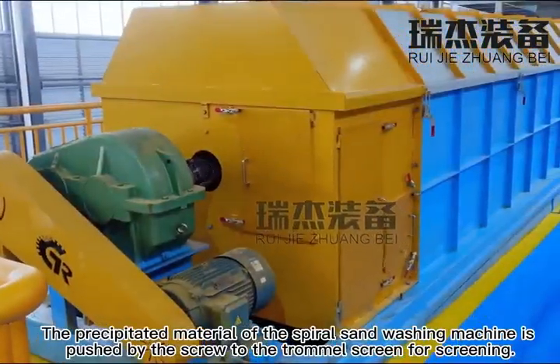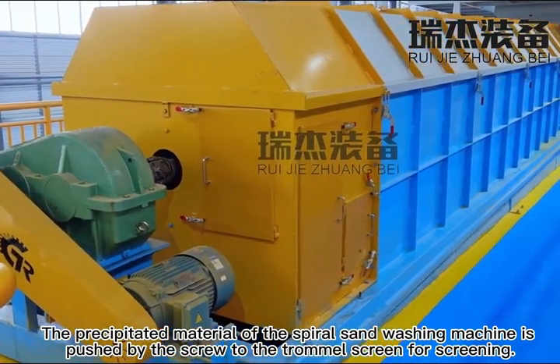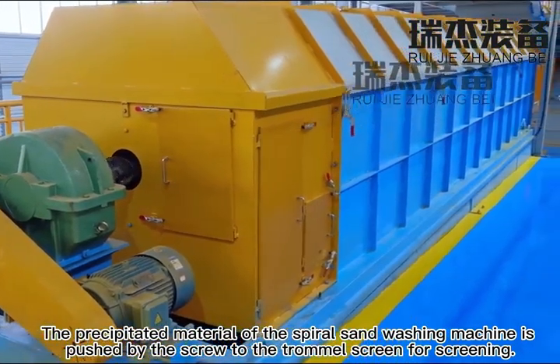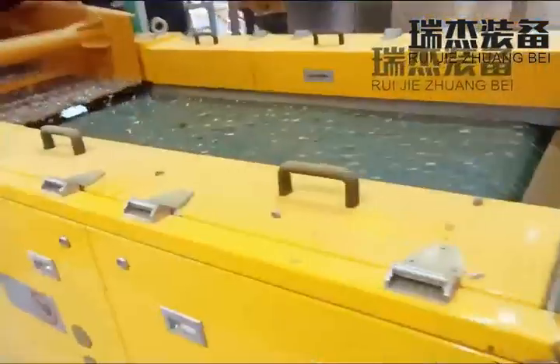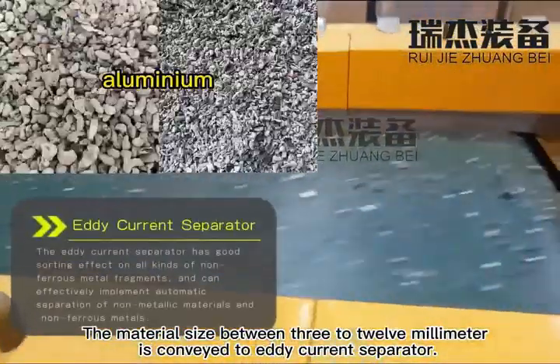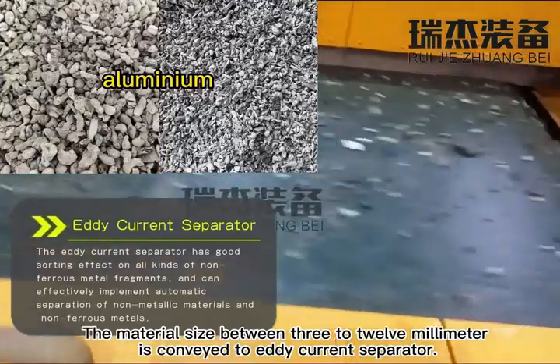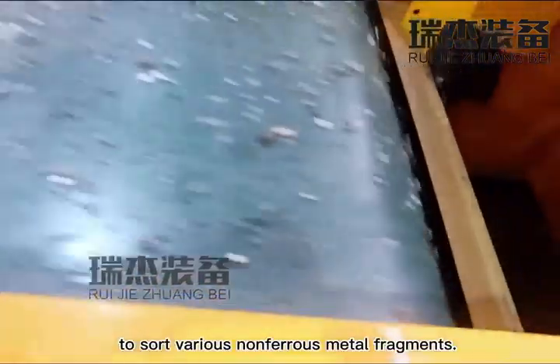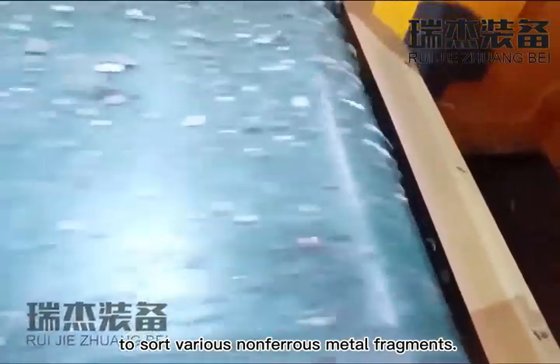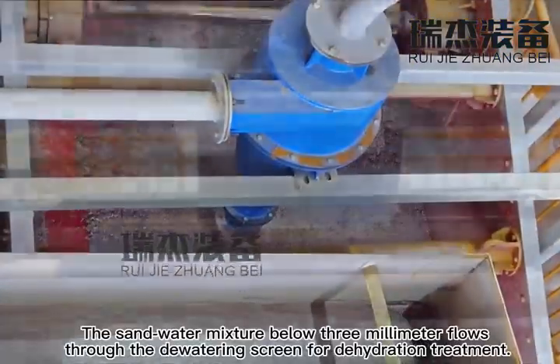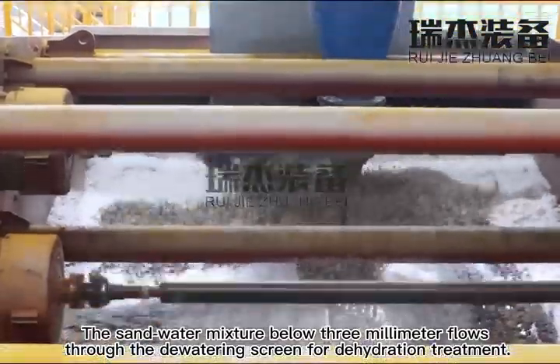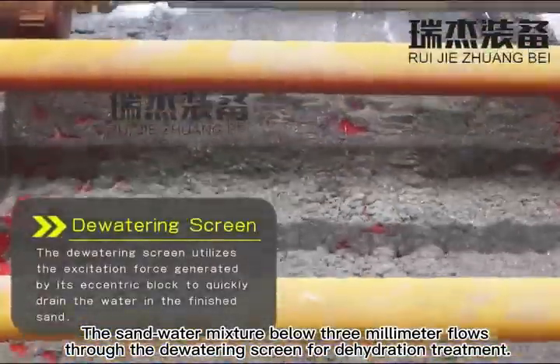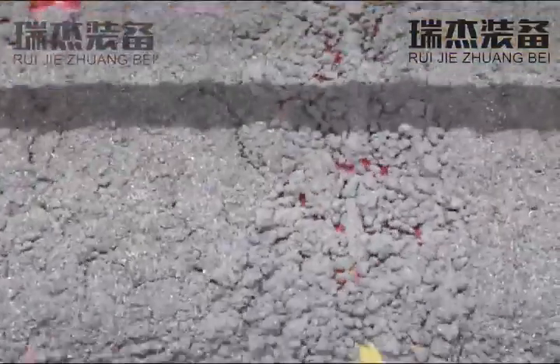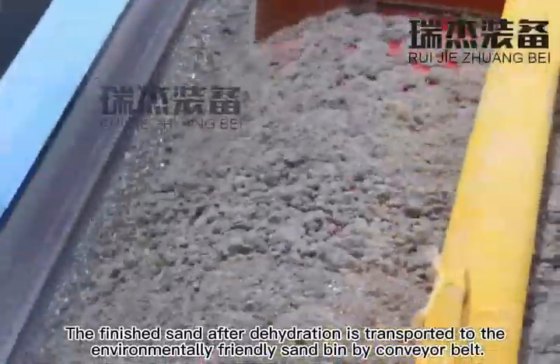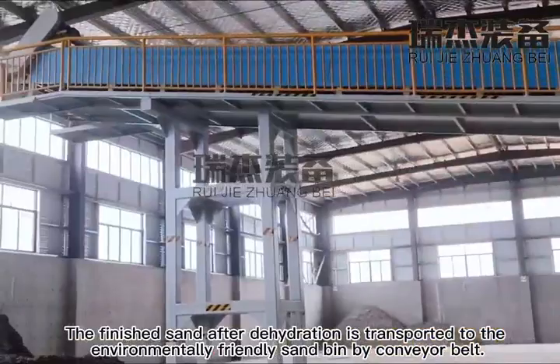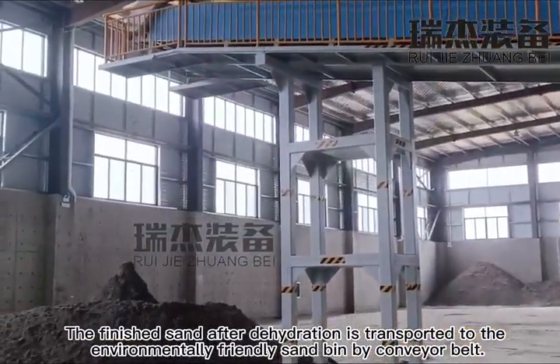The precipitated material of the spiral sand washing machine is pushed by the screw to the trommel screen for screening. The material size between 3 to 12 mm is conveyed to the eddy current separator to sort various non-ferrous metal fragments. The sand-water mixture below 3 mm flows through the dewatering screen for dehydration treatment. The finished sand after dehydration is transported to the environmentally friendly sand bin by conveyor belt.